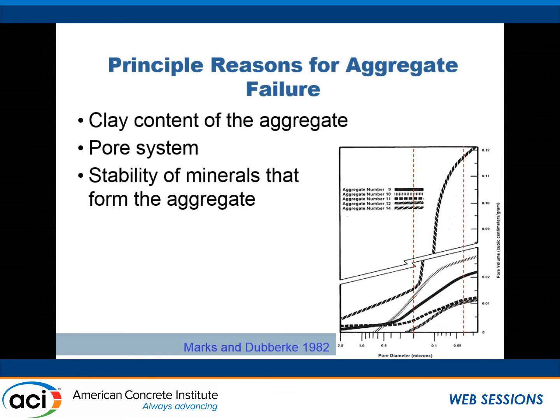Okay, so the pore size is pretty typical. Wendell actually produced quite a lot of data showing materials that were problematic had a fairly characteristic plot. Materials that were less problematic had a different plot. Just out of interest, I ran the same test on 0.4 water cement concrete. Guess which line it followed? The bad one. Oh dear.